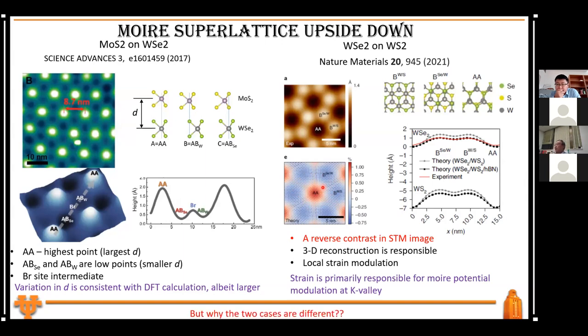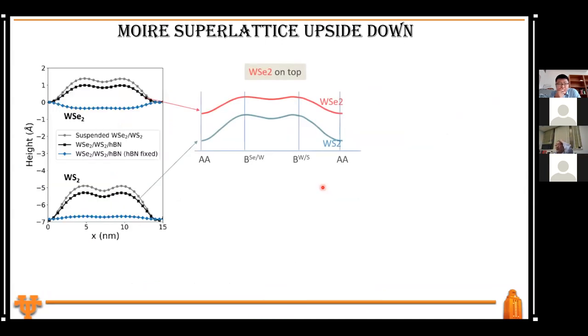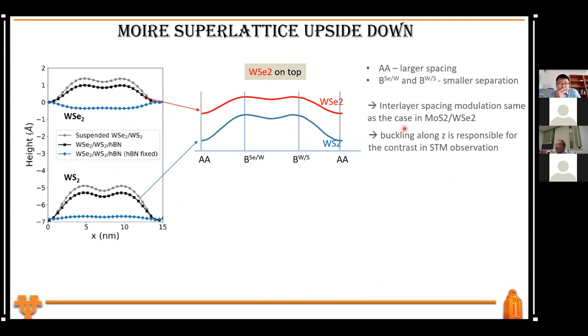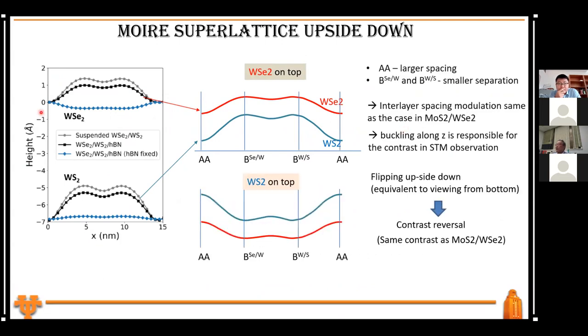So that is what I have observed. Okay, but I want to say, well, but why? We see the two different results, right? You cannot just say one is on top of the other, and then you just see different results. Until I look at this one and say, well, this is really a moiré superlattice upside down, right? If I take their result, AA is where you have a large interlayer spacing, but the strain pushed this one down. Now, in our case, what we observe is we have WSe2 on top. So if I take their result, but instead of viewing from the WSe2 side, my STM looks at it from the WS2 side, then indeed, at the AA site you have a large interlayer spacing, and you're going to see the high point. The strain also pushes the high point, okay?